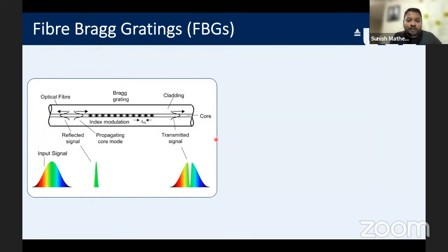Now, when there is talk about fiber optic sensors, you can't skip this part. Fiber Bragg gratings are the most popular sensors so far. So how are fiber Bragg gratings made? Fiber Bragg gratings are made by causing refractive index modulation inside the core. You apply a strong CO2 laser and cause refractive index modulation. These black points and white points are the points where the refractive index has gone through a slight modulation. As a result, when you put light into it, you get a strong reflection from a very narrow part of the spectrum. So that is the property of the Bragg grating.